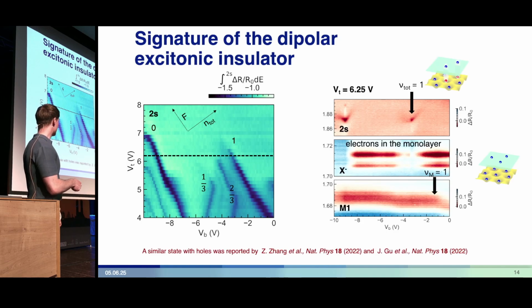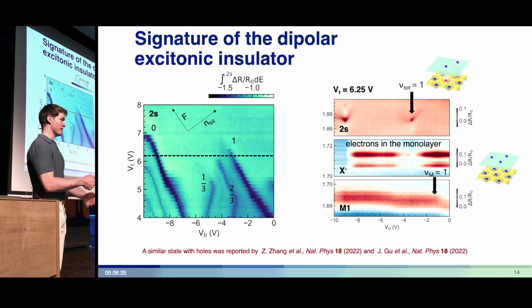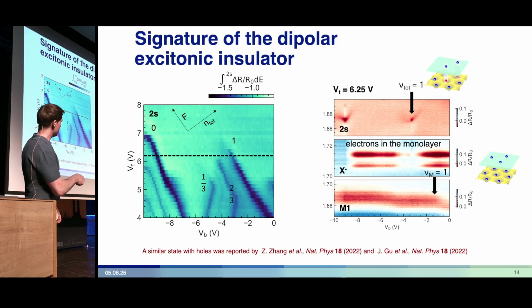If we then look at the other excitons in the system, the trion — this is a bit different. Now we actually see a trion signal indicating that between these states, and generally across this line cut, the monolayer has charges in it. But curiously, they actually disappear abruptly when we enter this correlated insulating phase detected by the 2s.